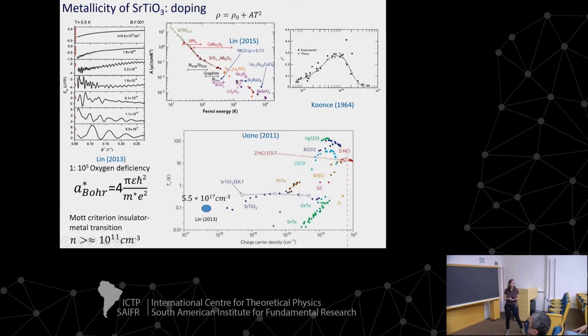This is the most dilute superconductor. Clearly, we can see that the critical temperature is quite low, therefore, from a technological point of view, it might not be very interesting, but it's still remarkable from a fundamental point of view. So if we look at the literature about fermiology and try to understand the main underlying mechanisms, there are many open and unanswered questions, because it's very difficult to establish what the main mechanism is at the point in which we have such a low level of electrons.